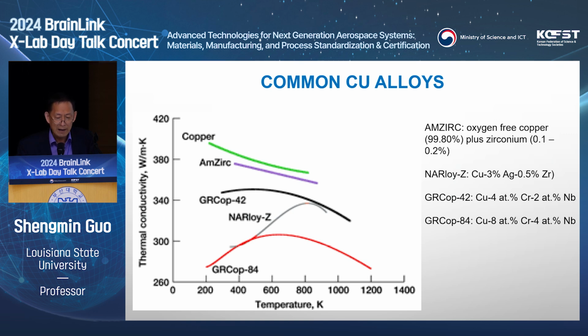You may say, how about adding some alloy elements to make it stronger? Yes, NASA thought about this many, many years ago. For example, one copper alloy is 99.8% pure copper plus maybe 0.1 to 0.2% of zirconium. That sounds like a pretty good option, it gives you good thermal conductivity. However, the mechanical strength is not good enough. On this chart, you will find the recent development of NASA GR-COP 42 and 84, two NASA copper alloys, which give us reasonably good thermal conductivity. For example, GR-COP 42 gives you a conductivity value around 340 watts per meter Kelvin. That's not too far away from 380, that's pure copper, because as I said, pure copper will not give you good mechanical strength as soon as you